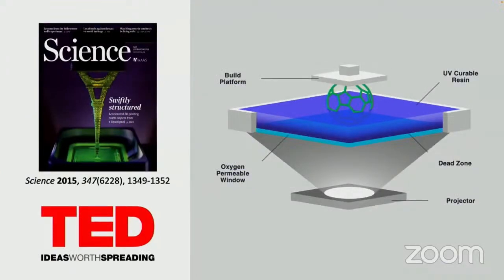So about 7 years ago now, we published this paper and gave a talk at TED about a new approach for 3D printing that we refer to as continuous liquid interface production. So it's basically an XY projection from a DLP projector, and we're using light at 385 nanometers. At the bottom of this reservoir is a very special window. It's not only optically transparent, but it's also permeable to oxygen. And oxygen, those of you who are familiar with free radical polymerization, oxygen's an inhibitor for free radical polymerizations. When you hear about polymerizing a monomer, you often degas the monomer. Well, you're removing the oxygen so that you can kick off the polymerization.